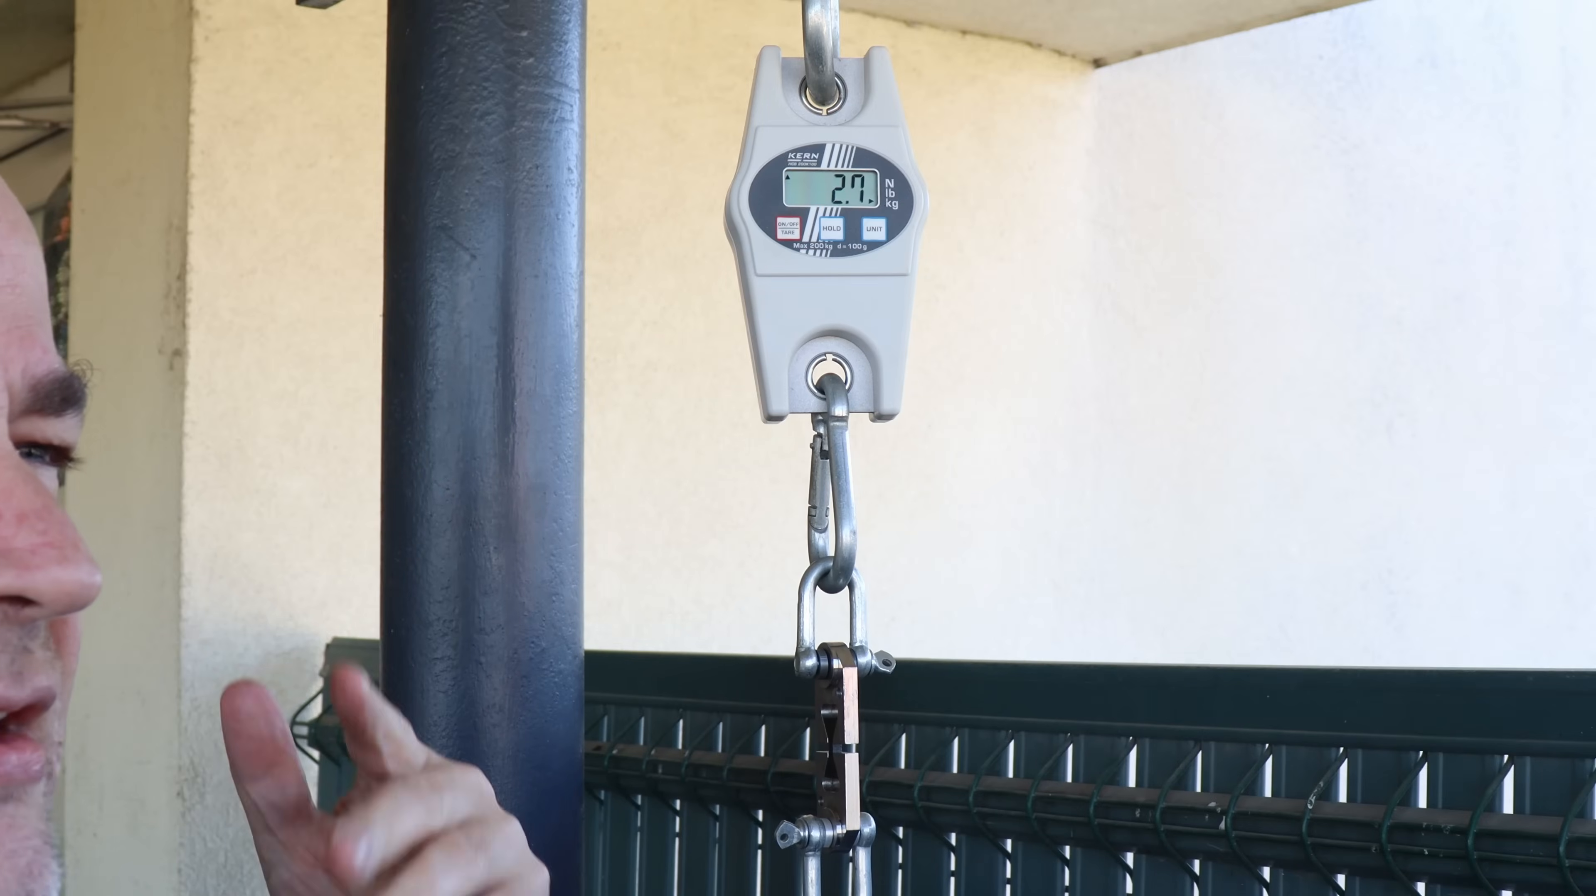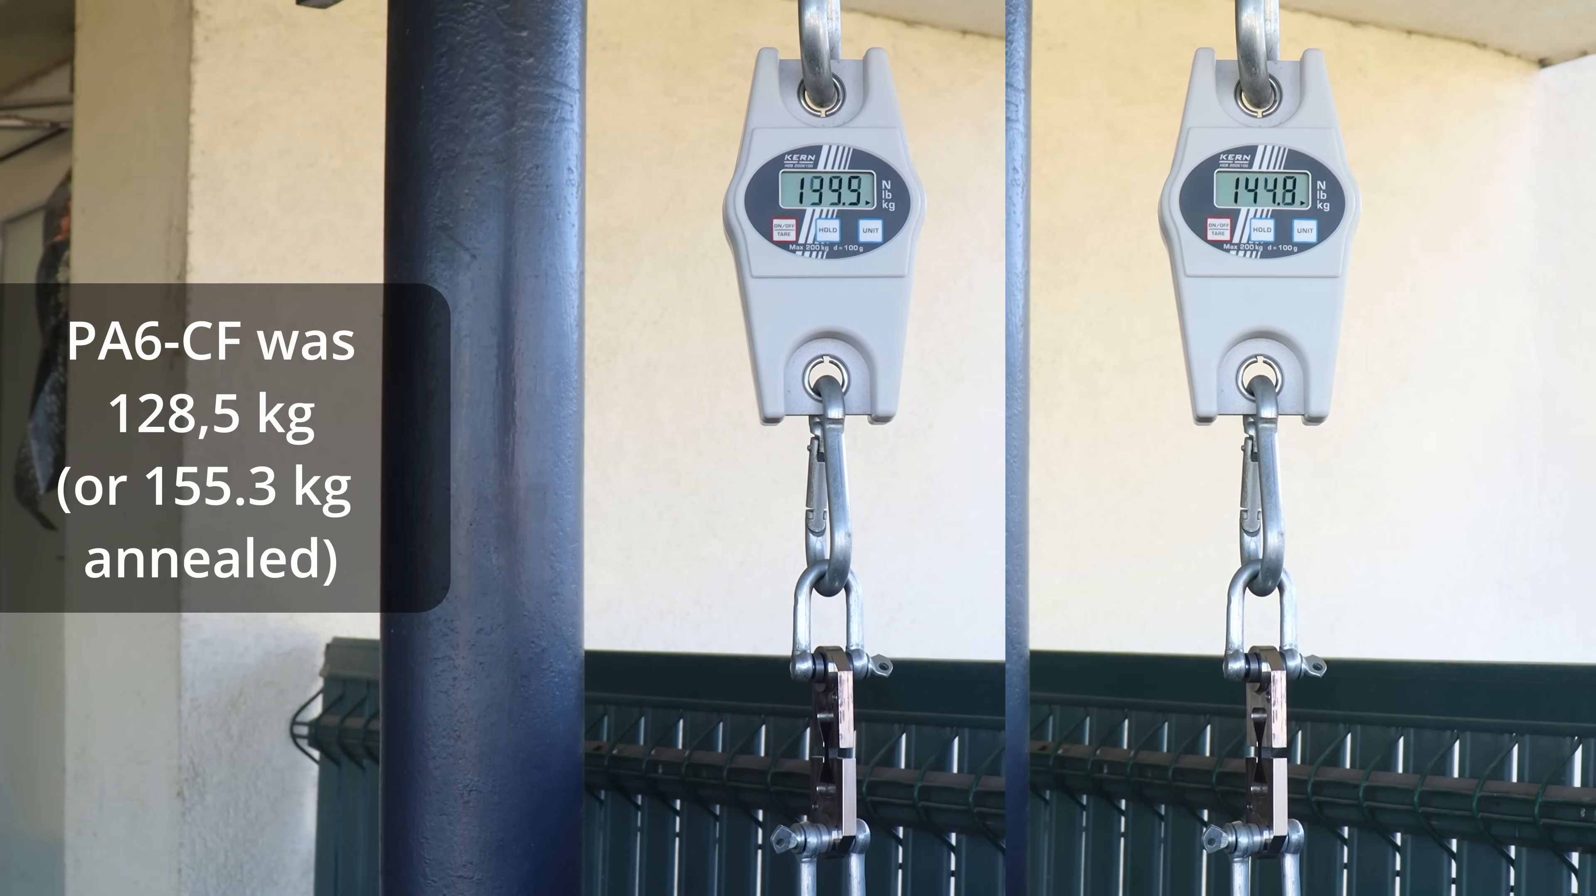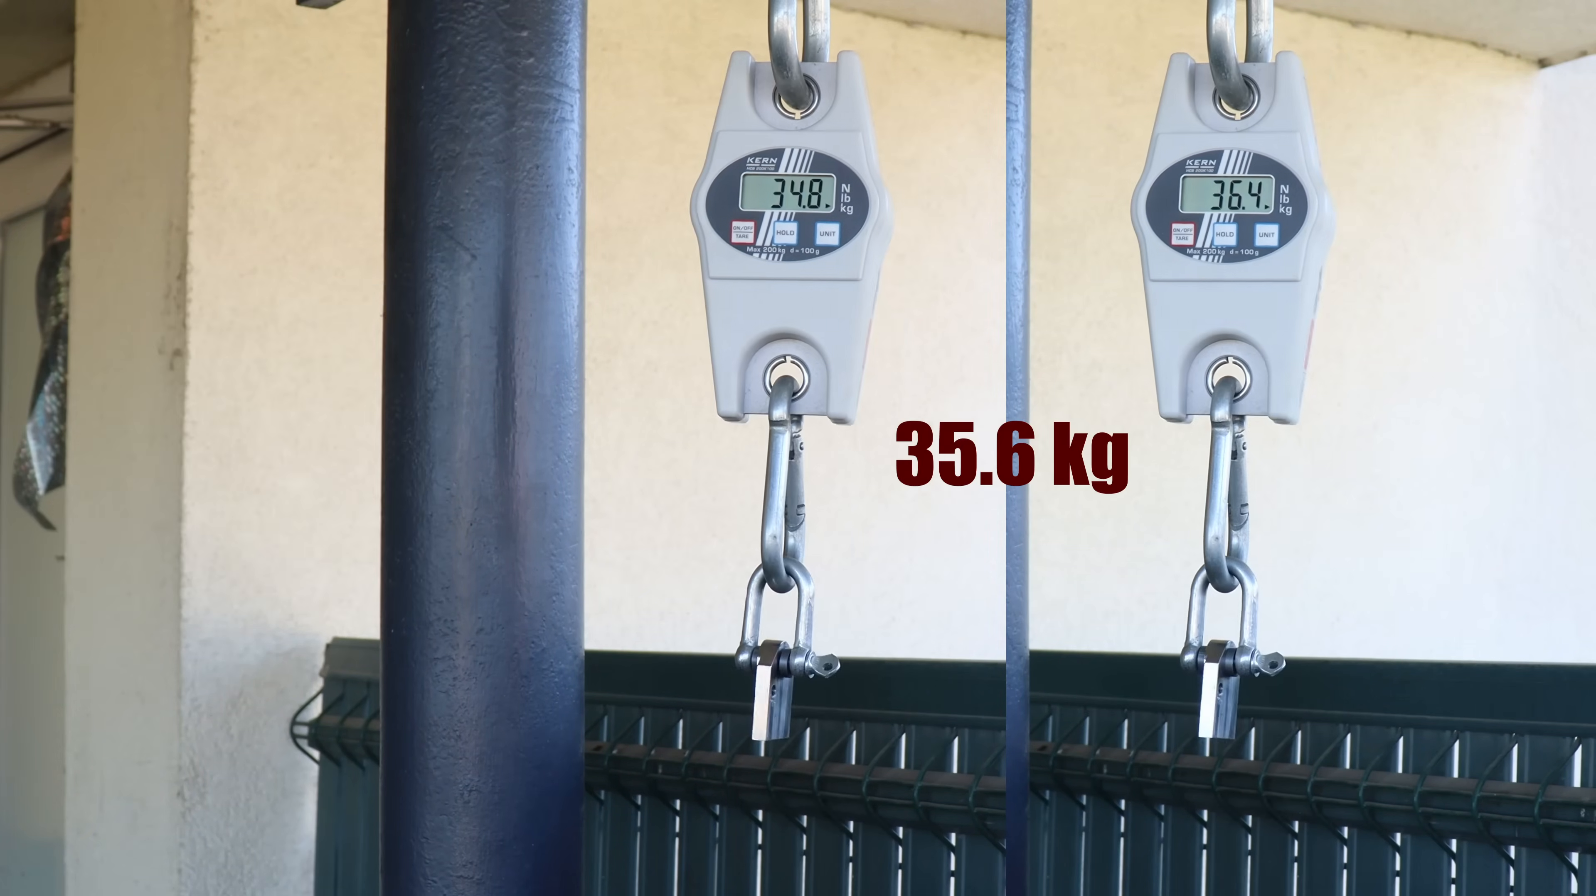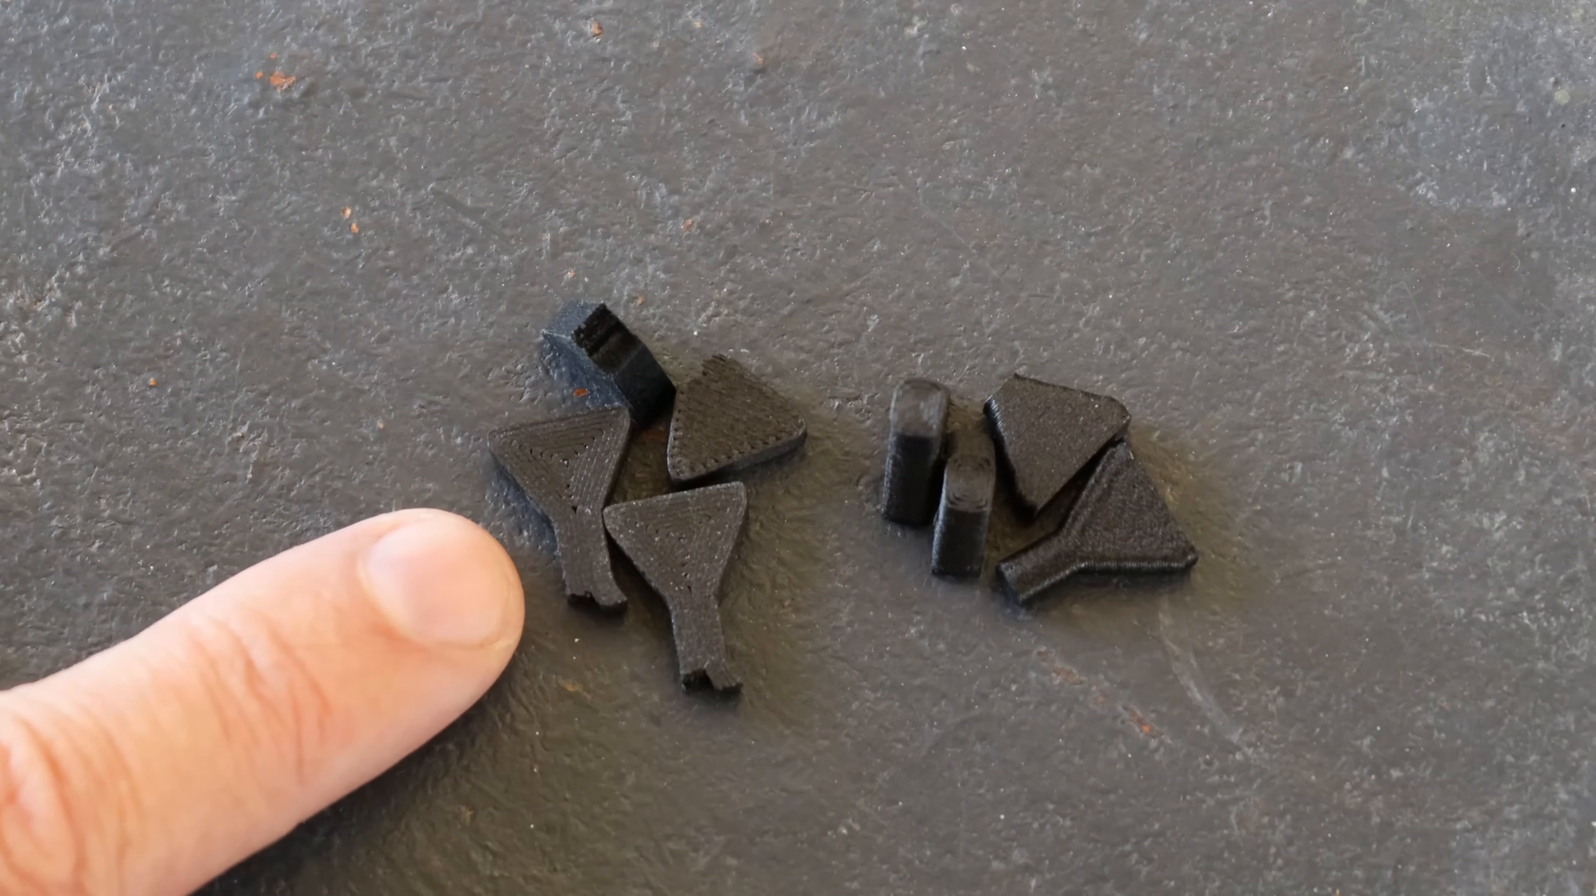The tensile test and the maximum on this scale is 200 kg. I hope it will be enough. Printed in horizontal position, and for the reference you can see the PA6-CF numbers. And this is the average value, very strong material. Layer adhesion with vertically printed objects. Good, but compared to the XY much weaker. A good layer adhesion, but extremely strong in XY direction on the tensile test. This means that you have to pay attention to the design, because it is much stronger along the XY axis compared to the Z axis.